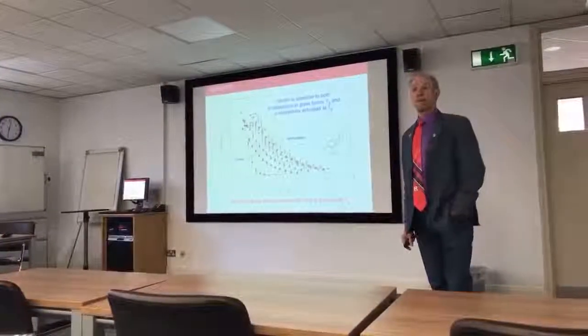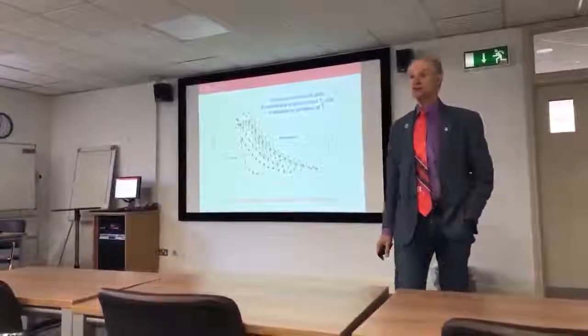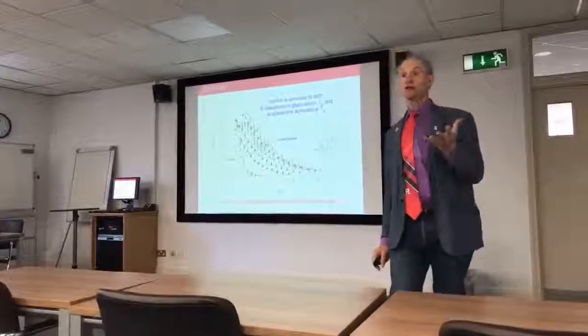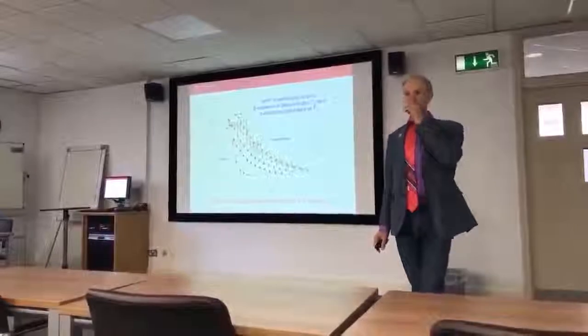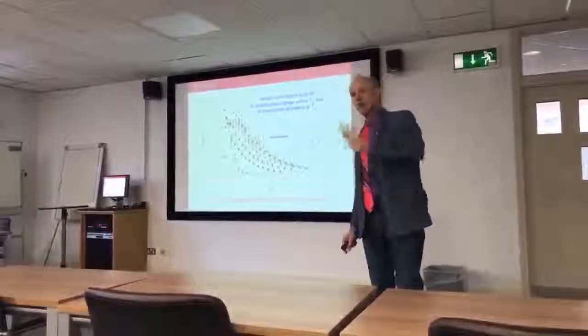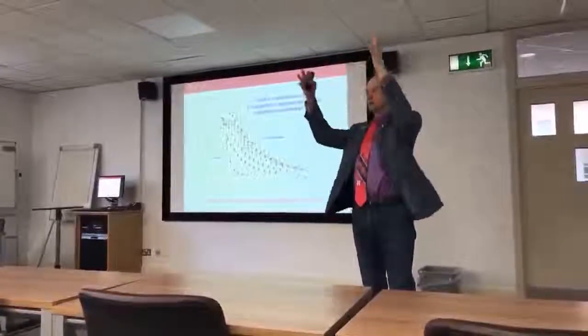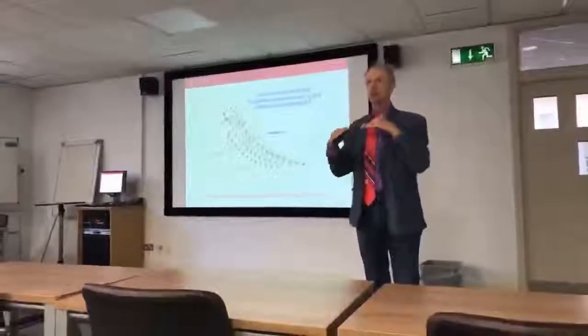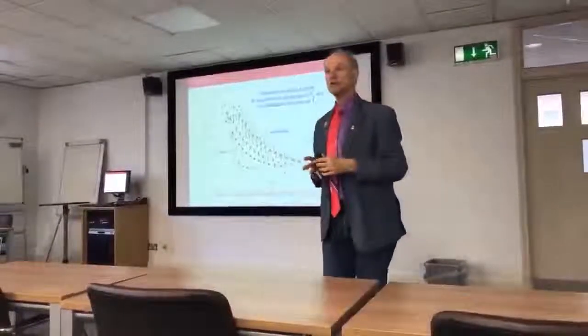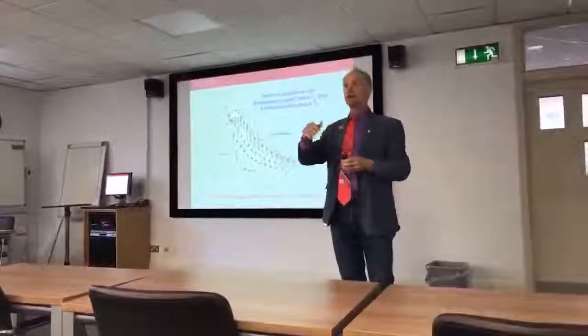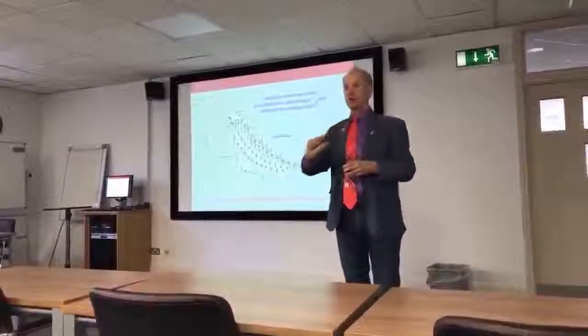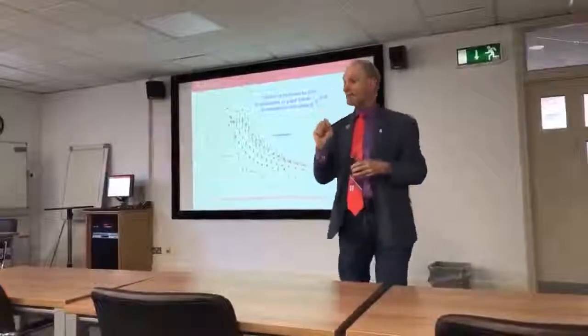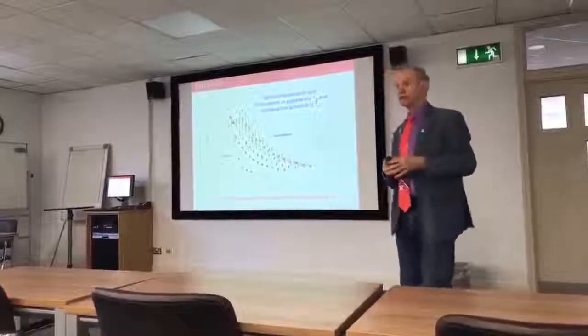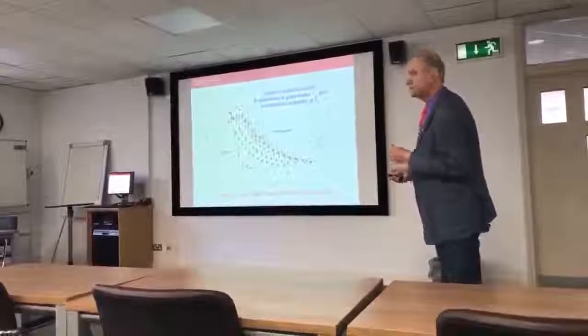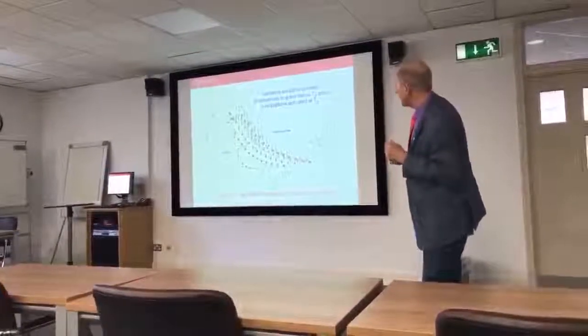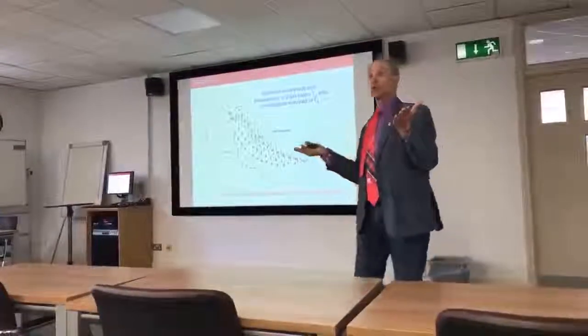Question? So what's TG? I just missed the point. The glass transition temperature of the amorphous solid matrix. Okay. Yeah, so basically, with these sugars, when you dry them down, we take them from solution, we dry them onto a quartz slide, and when you dry these sugars down, they do not crystallize, they actually just form an amorphous matrix. So it forms a glassy state rather than a crystalline state. So it's a glassy glucose. Of course, once we've heated it up above the TG, it will crystallize.